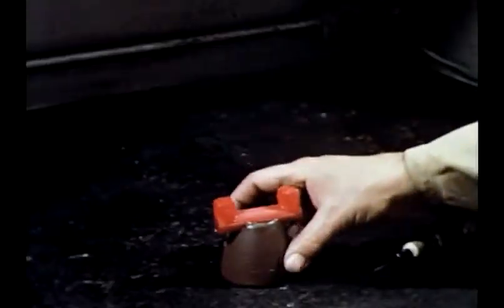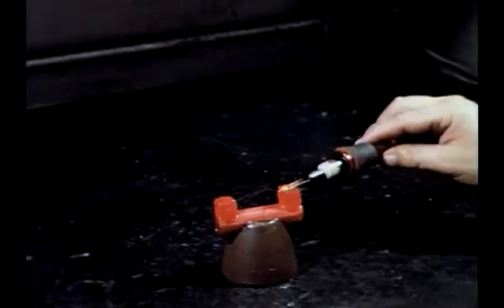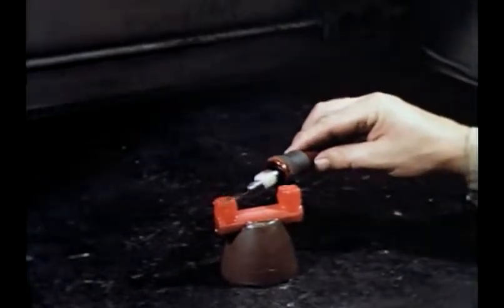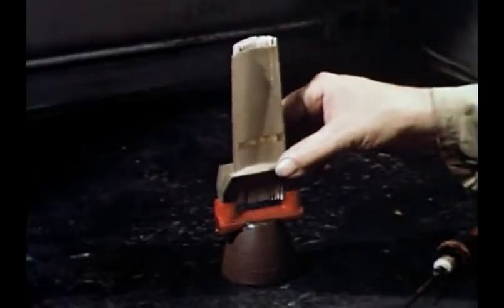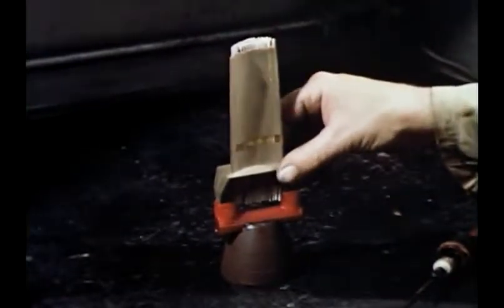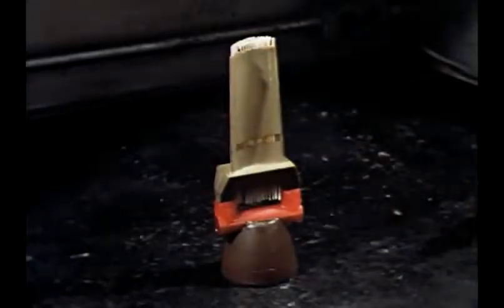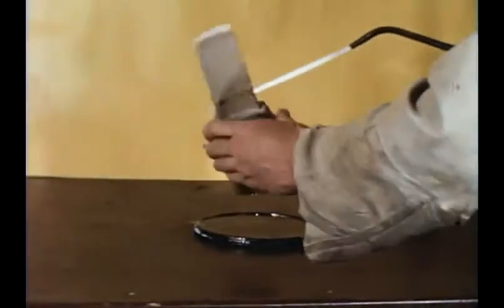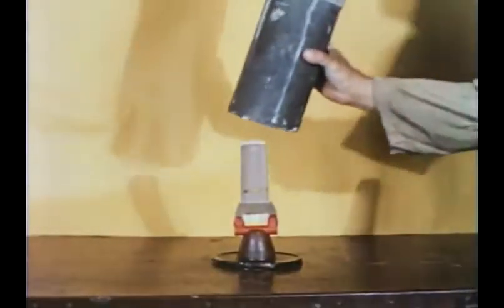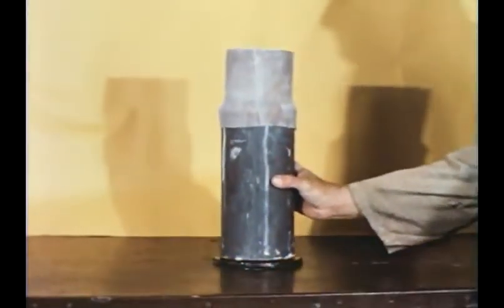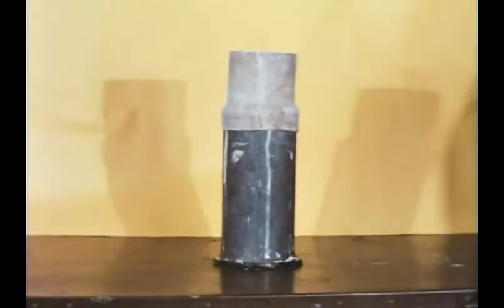Additional pieces of wax are assembled by welding with a hot wire. These pieces will form sprues, runners, and ingates or passages for the molten metal to reach the blade cavity in the casting mold. The assembled wax is mounted on a waxed base to seal it. A can-type flask is placed over the assembly, and it too is sealed at the bottom.